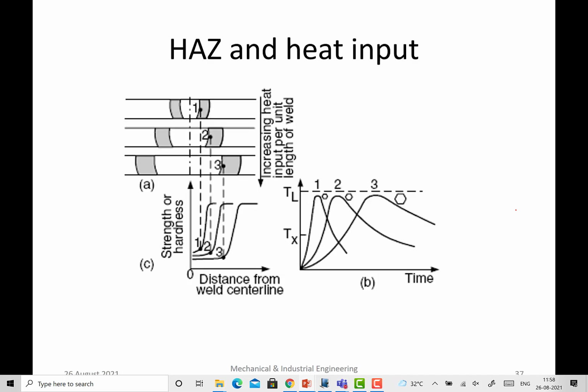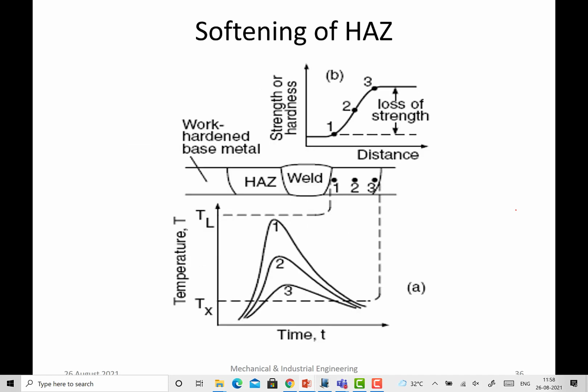So I think this is not indicating. This one will be more helpful to explain what I want to say. Let's talk about this. This is what I have just said: the zones which are at different distances from the weld nugget area will be experiencing different temperatures. So increasing temperatures at location 1, peak temperature is high, location 2, peak temperature is somewhat lower, further lower. And beyond this, the base metal is really not affected, so your strength is really good.